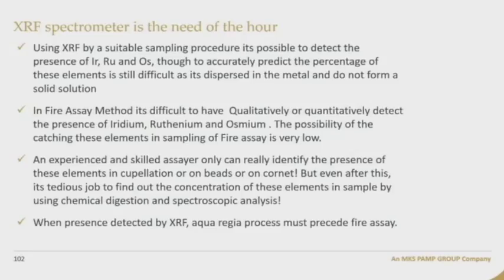So what do we infer? We infer that using XRF with a suitable sampling procedure, it is possible to detect the presence of iridium, ruthenium, osmium, though to accurately predict the percentage of these elements is still difficult, as they are dispersed in the metal and do not form a solid solution. In the fire assay method, it's difficult to qualitatively or quantitatively detect the presence of these PGMs. The possibility of catching these elements in sampling of fire assay is very low.